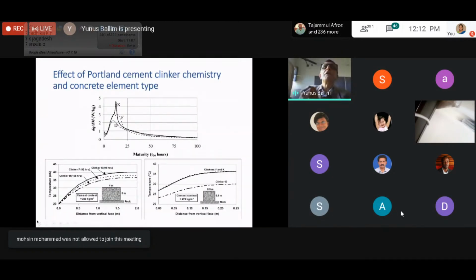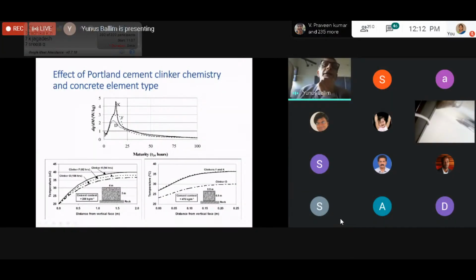Just to give you some effects of using the model, of course, some effect of difference. So remember I said to you that not all Portland cements are born the same. Here I chose 3 different sort of a low, medium and a high peak heat rate cements. And you can see that in a large concrete element, 4 meters by 3 meters, using 200 kilograms of cement per cubic meter, if you use those 3 different Portland cements, those are the heat rates you'll get at the center across a cross section, when the peak temperature occurs.